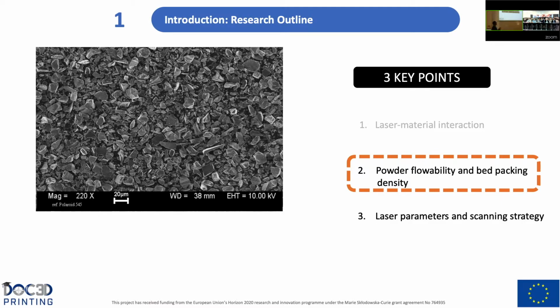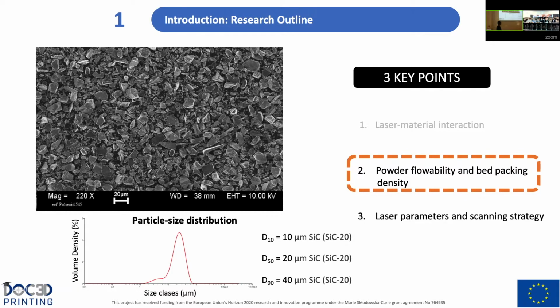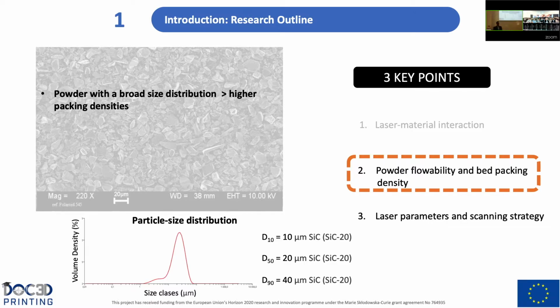Specific to this work, we are using this powder, which has a certain morphology. Regarding the particle size distribution, we can see that we have a D50 of 20 micrometers. But actually, here we know that a powder with a broad size distribution will increase the packing density. And moreover, the more spherical the morphology of the powder, the better the powder flowability. At this point, we didn't focus on this, and at the end of this presentation, in the section on future challenges and perspectives, we will see that we have some work to do.